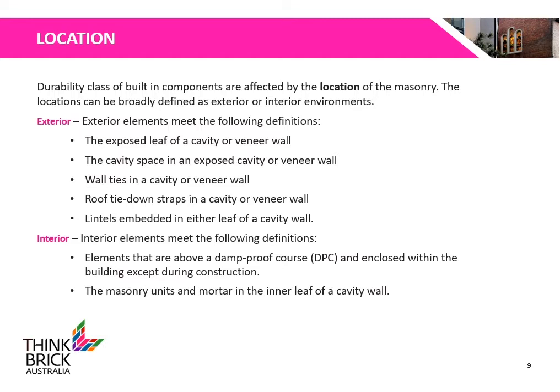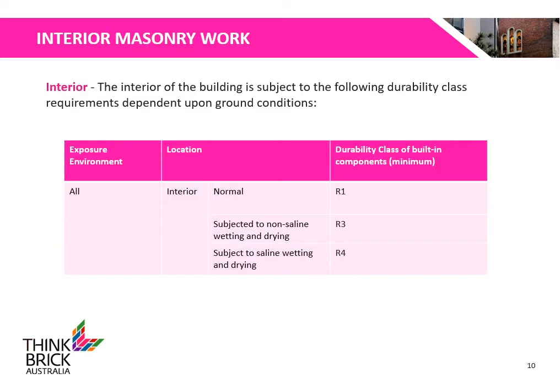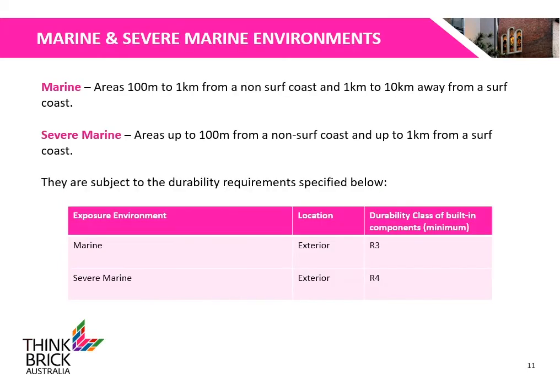Locations can be broadly defined as exterior or interior environments, and exterior and interior elements must meet the definitions shown. Marine environments are defined as areas 100m to 1km away from a non-surf coast, and 1km to 10km away from a surf coast. Severe marine environments are defined as areas up to 100m from a non-surf coast, and up to 1km from a surf coast.